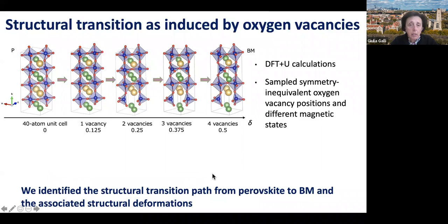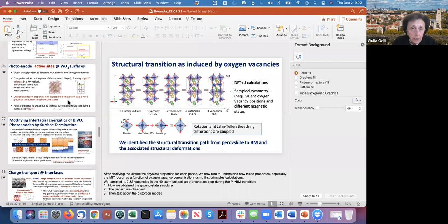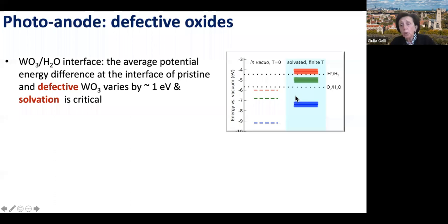I'm sorry, let me do this differently. So basically, if you know the position of the top of the valence band of the oxide, determined by doing the calculation of your interface, relative to the oxidation potential of water, which here would be this thick blue line, relative to the oxygen. If you know that, then, of course, why are these lines thick? Because these contain the fluctuation also at finite temperature, and also the averages that in our case are not super good, but if you know that number, then by using the Nernst equation you can know the overpotential.